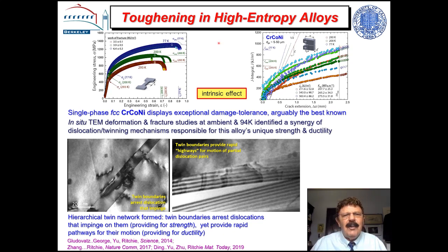How is this achieved? It's achieved through steady strain hardening, which hardens the material, but the strain hardening delays necking, so you generate ductility. So there are deformation mechanisms here that promote ductility and strength, the duality of function, by a synergy of deformation mechanisms. You can see a few here.